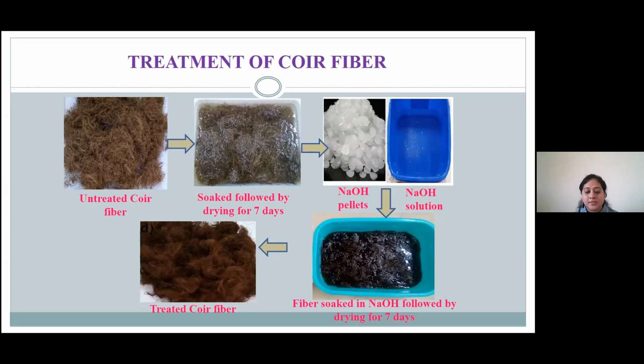Then these dried fibers are soaked in sodium hydroxide solution for 7 days. The soaked fibers are then removed from the solution, washed with water properly to remove the residual alkali from the fiber surfaces, and then again kept for drying for 7 days at standard temperature.